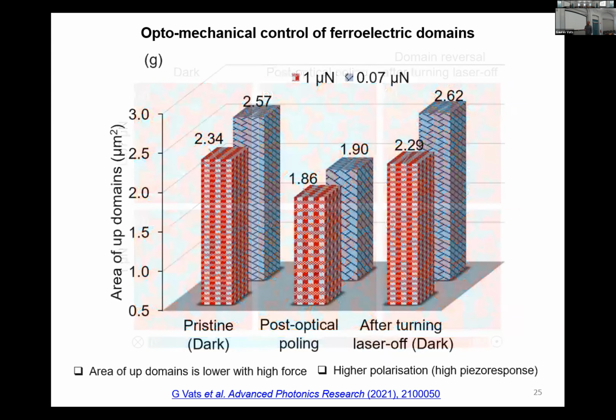Again, I did some statistics on this. So what I'm plotting is the area of the up red domains. This is with the 0.07 micronewton. This is with the 1 micronewton. Post optical poling, there is a change. There is a clear difference. Other differences are also there, but that we have already understood. Because of mechanical stress, there is a change in domain population. But when we do both light and mechanical force, there is a change, and that change is again an indication of a change in piezo response.